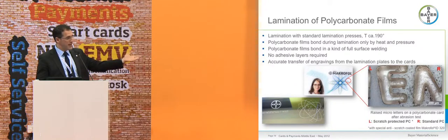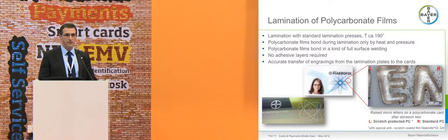Additionally, it is very easy to transfer engraved security features from the lamination plates onto the document surface, even if they are in a size of 0.1, 0.2 millimeters. It is very good to emboss the surface of the polycarbonate document.